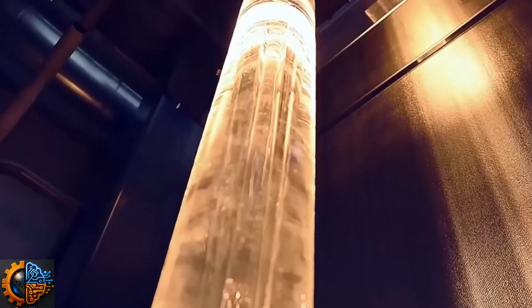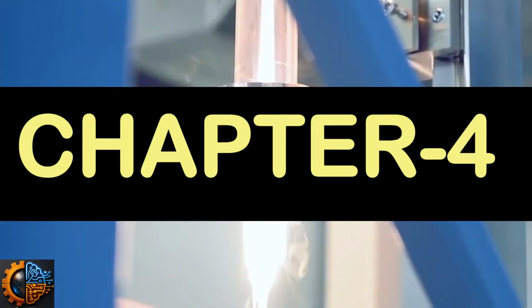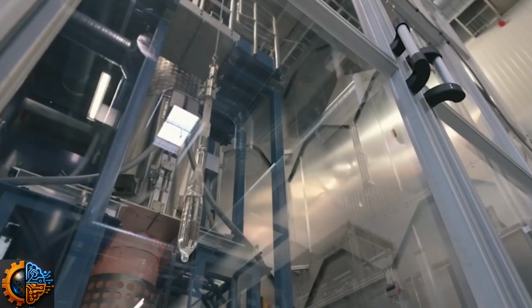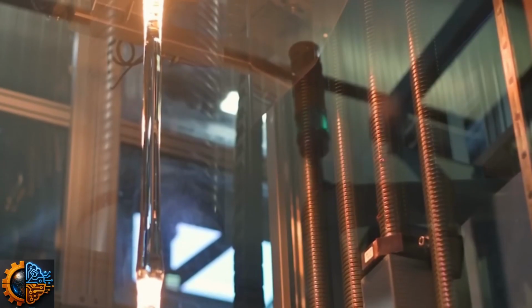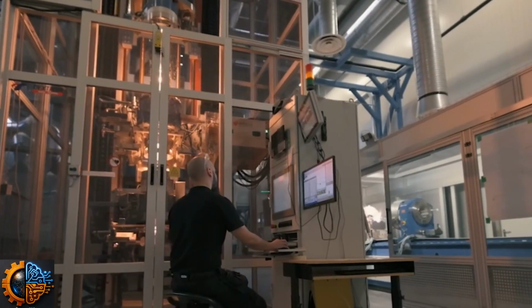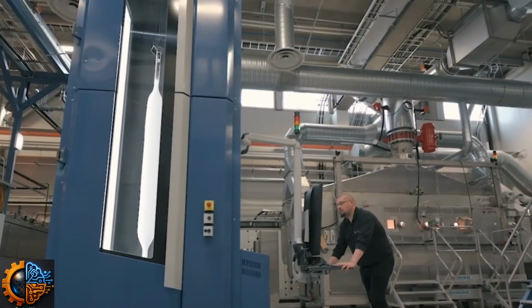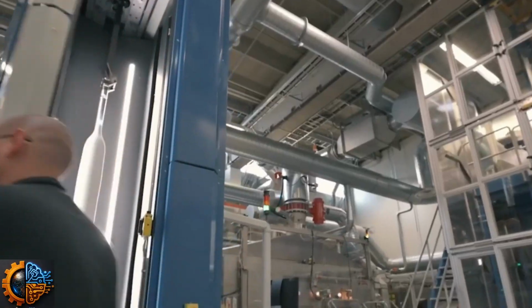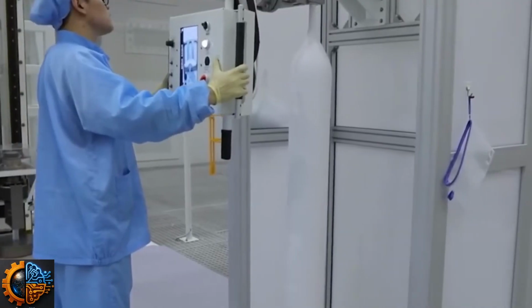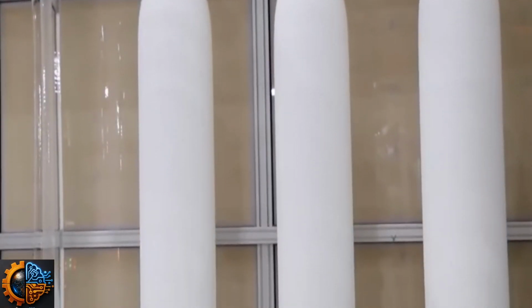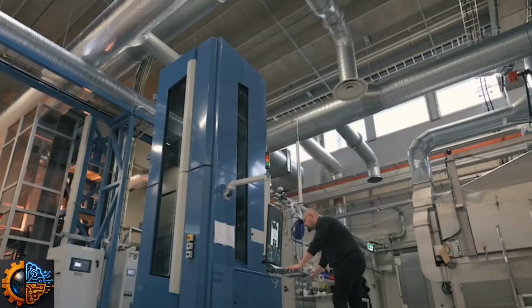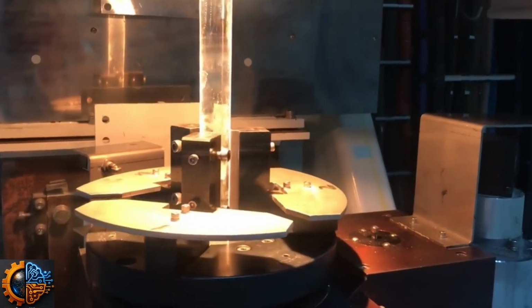Chapter 4: Manufacturing the Glass Preform. Now, the factory begins producing the heart of every optical fiber, the glass preform. A hollow silica tube is mounted onto a rotating lathe. Specialized gases containing ultra-pure silicon compounds are introduced into the tube. At the same time, a flame reaching nearly 3,600 degrees Fahrenheit travels slowly across its surface. Inside the tube, chemical reactions create microscopic layers of glass.